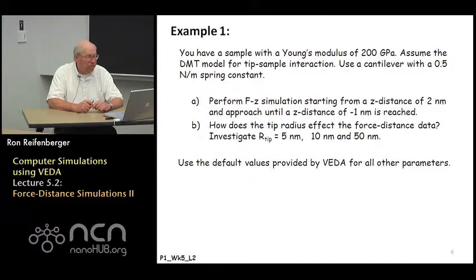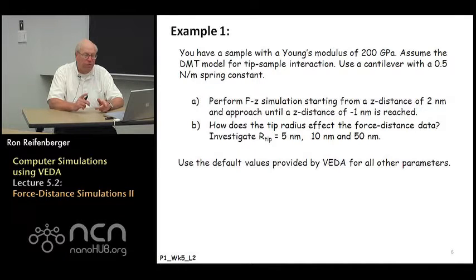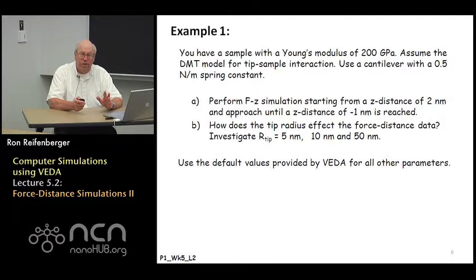We're going to run simulations from plus two nanometers to minus one nanometer for Z. For the DMT model the approach and retract curves are identical — there's no hysteretic behavior, so there's no reason to simulate the withdrawal curve. We're going to look at three different tip radii: 5, 10, and 50 nanometers, to see how the approach curve varies. All other parameters will use the default values.